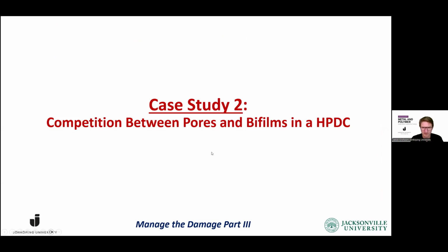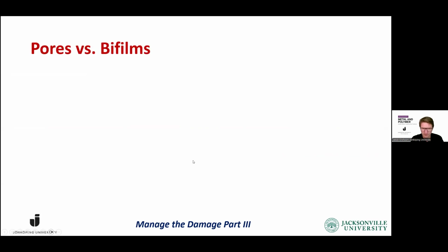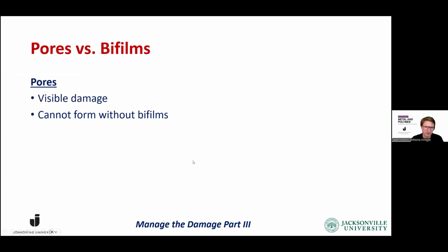So we said that these were samples that were also X-rayed, where we could confirm that there was no visible porosity in the samples. But at the same time as we produced those samples, we also played around with the settings so that we also got some samples where we had forced pores within the samples. So we're going to take a look at them also. This is work that we are just publishing also together with Murat here.